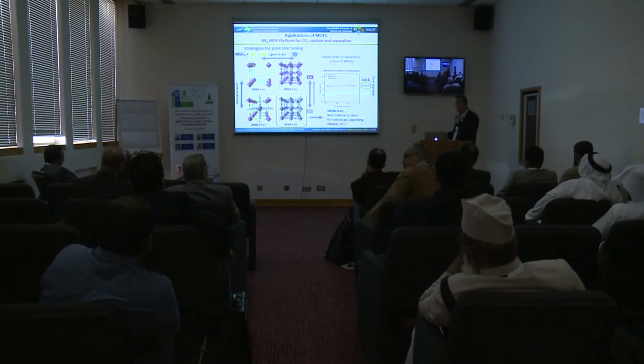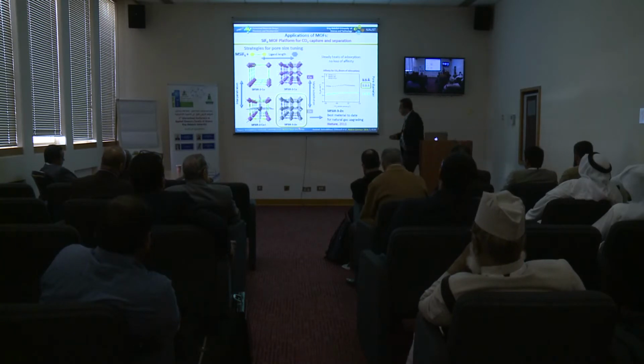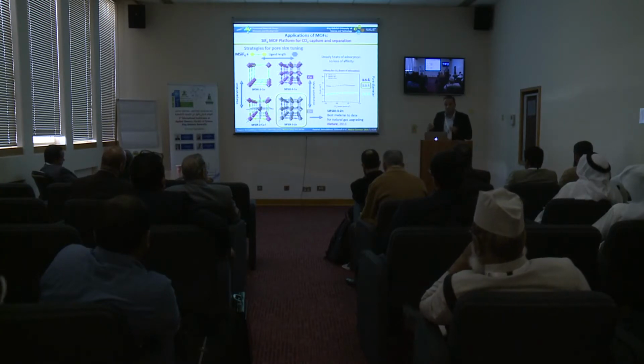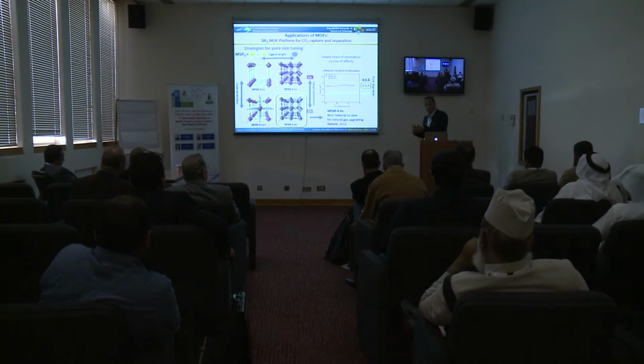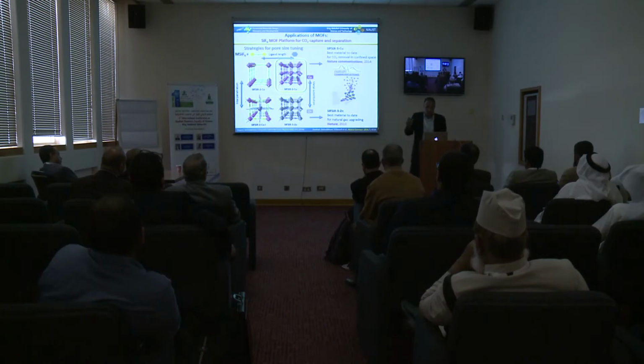But what's interesting, by using this coordination chemistry approach, by going from zinc to copper, we can take advantage of the Jahn-Teller effect. We can have one set of the bonds that's shorter than the other one. We're hoping that we can reduce this even further. And sure enough, we can go from 3.9 to 3.5 and enhance even further this heat of adsorption. And again, we are talking about physisorption here. All these gases can come just by reducing the pressure, and it's done. And this material today is the benchmark for removing CO2 from the air. You just put this material outside and you just suck CO2 from there.